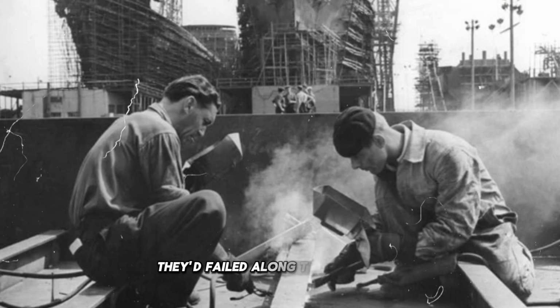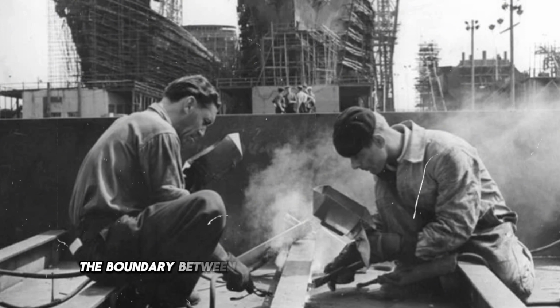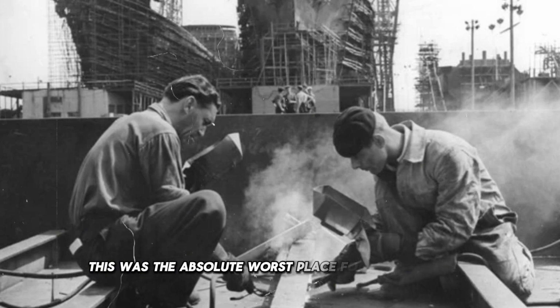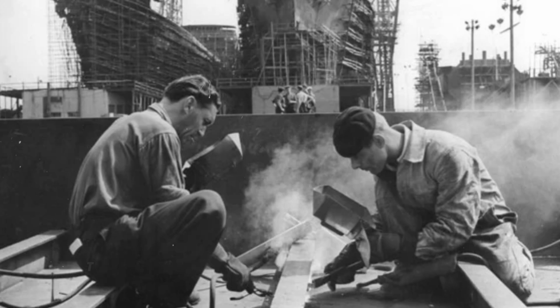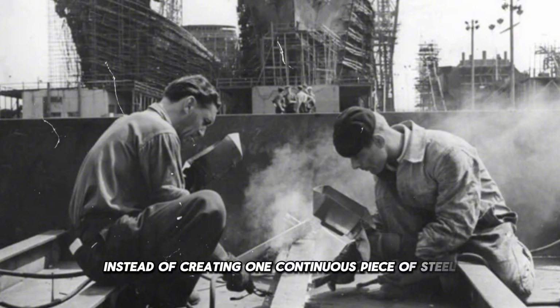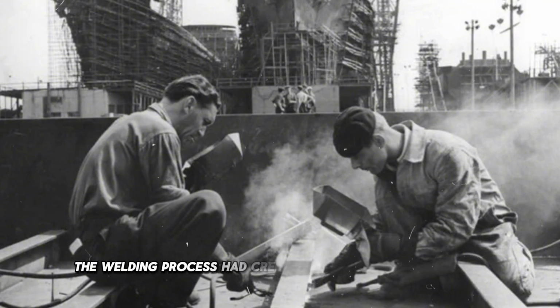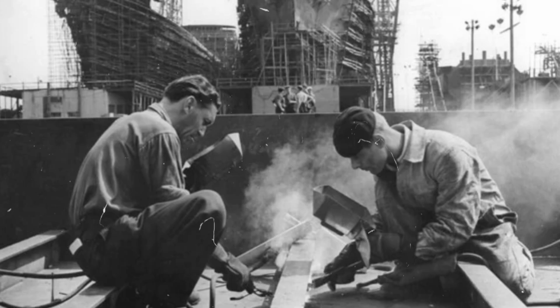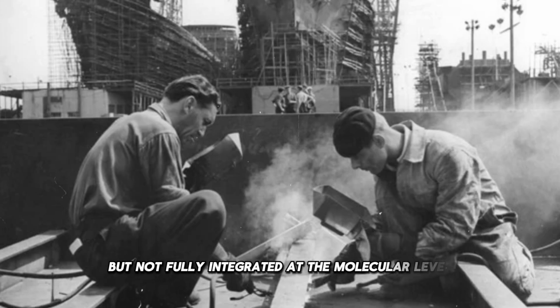They'd failed along the fusion line, the boundary between the weld metal and the base plate. This was the absolute worst place for a weld to fail, because it meant the weld hadn't truly bonded with the parent material. Instead of creating one continuous piece of steel, the welding process had created what metallurgists call a mechanical interlock, 2 pieces of metal pressed together but not fully integrated at the molecular level.